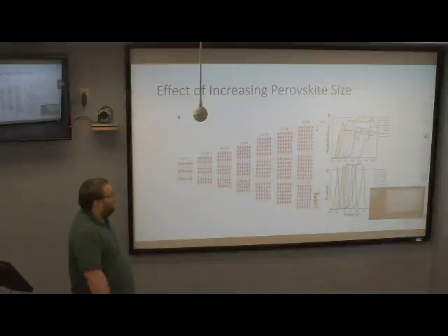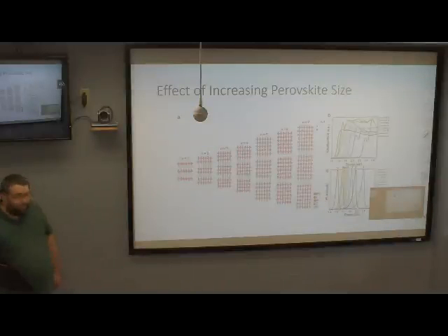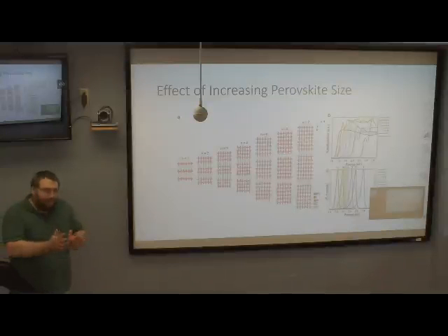As we increase the perovskite layer size, we increase the size of our box, and because of that, it redshifts the absorption and emission. Or if one thinks in the opposite way, if the length of the layer is infinite, it is the fundamental gap. As soon as you go the opposite direction, making it thinner and thinner, it blue shifts. If you go from 3D and start confining it, it'll blue shift.